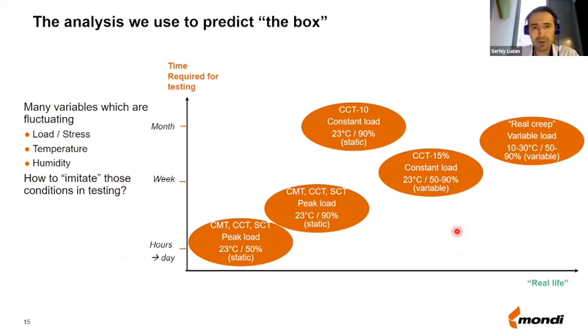So far we have only spoken about the tests which are performed immediately, so-called peak load resistance. Whether we do this test at 50% relative humidity or at 90% relative humidity, in real life we never have static conditions. And therefore, even though these tests can be done relatively quickly, if we imagine a scale of how well the tests replicate real life conditions, the peak load tests are relatively far from real life conditions. Yes, they can be done quickly, but they are relatively far from real life.